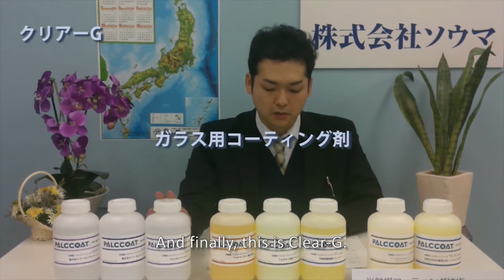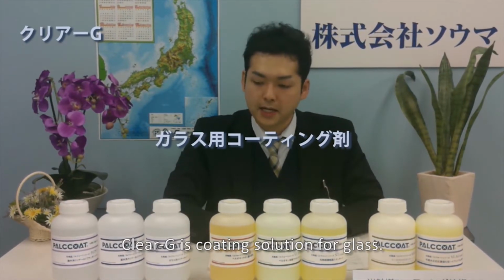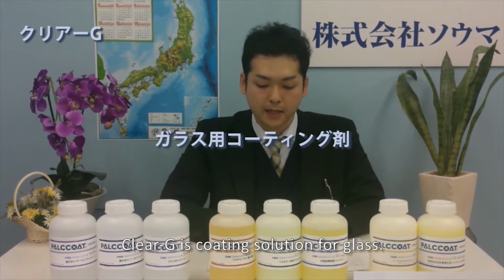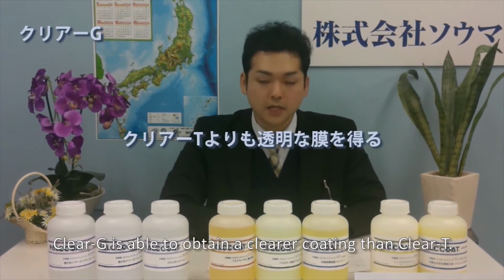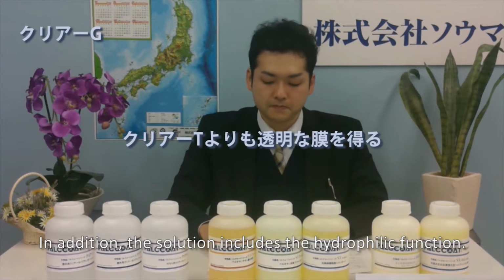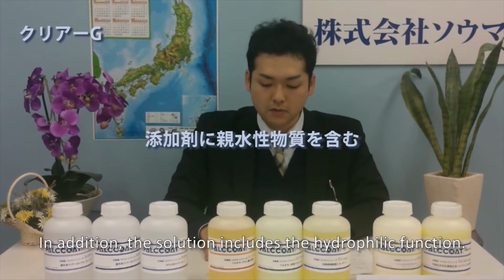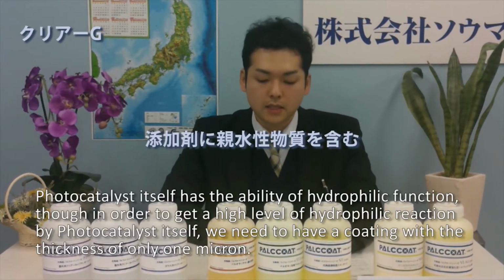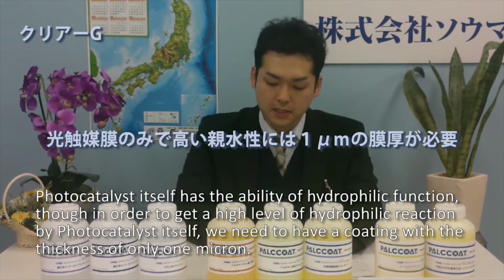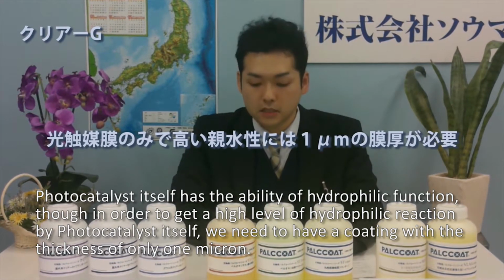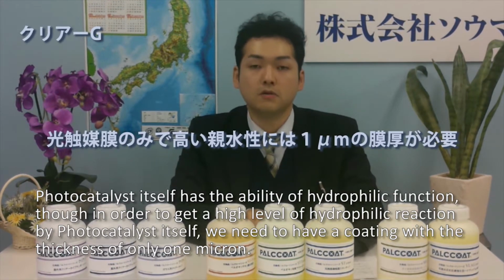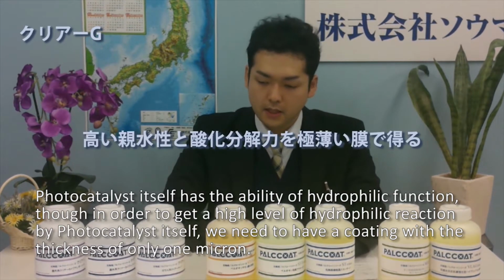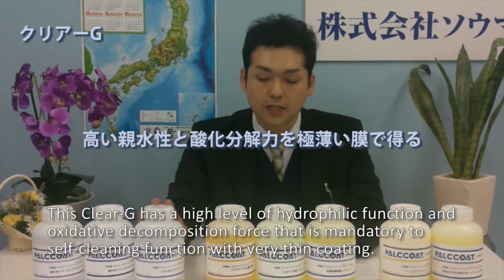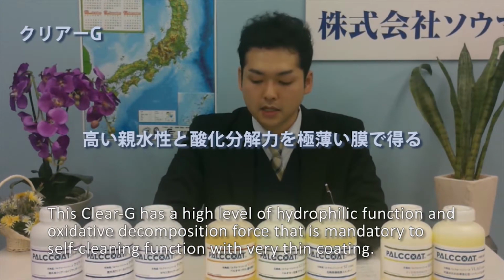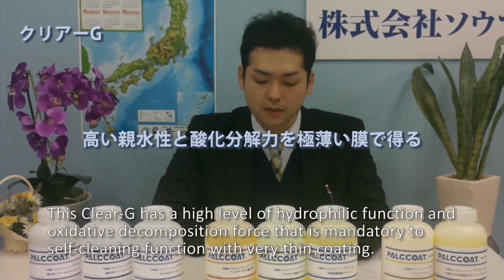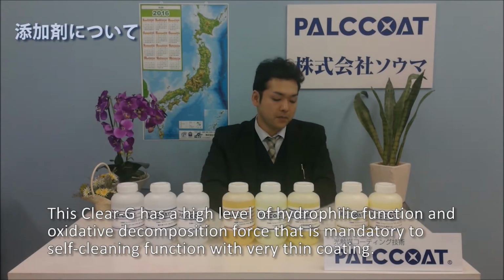And finally, this is the clear G. Clear G is coating solution for glass. Clear G is able to obtain a clearer coating than clear T. In addition to solution, it includes the hydrophilic function. Photocatalyst itself has the ability of hydrophilic function, though in order to get a high level of hydrophilic reaction by photocatalyst itself, we need to have a coating with thickness of only 1 micron. This clear G has a high level of hydrophilic function and oxidative decomposition force that is mandatory to self-cleaning function with very thin coating.